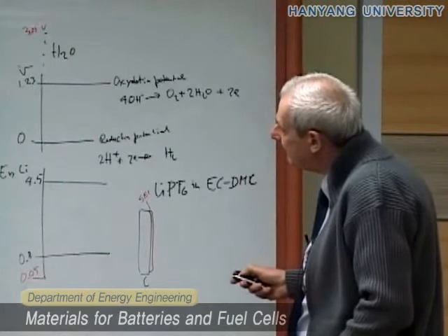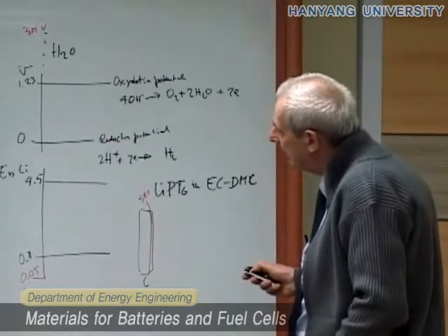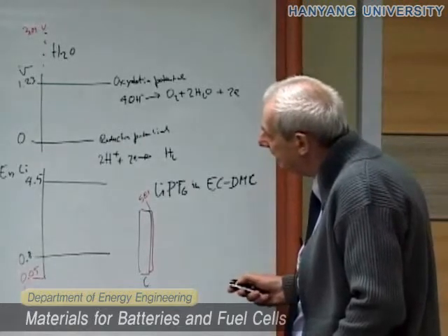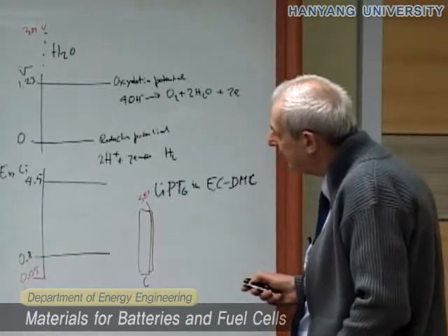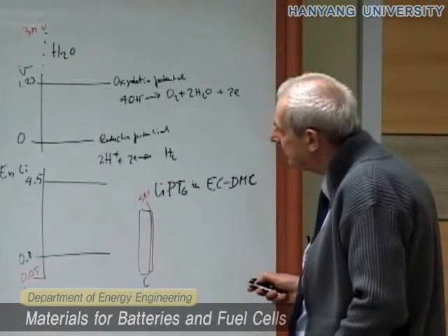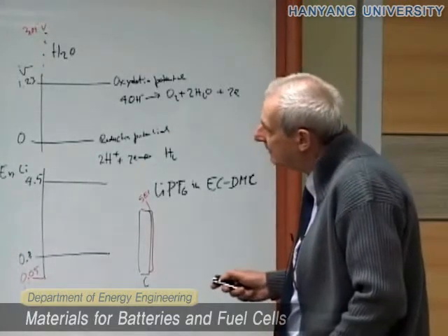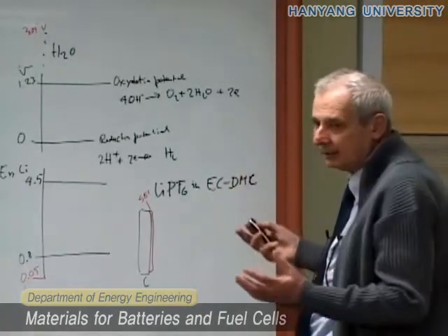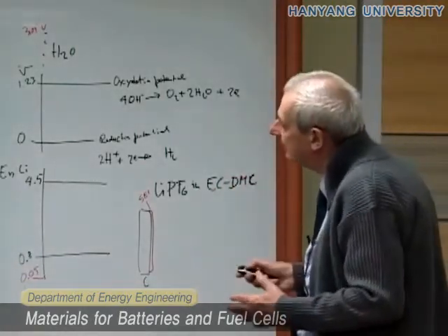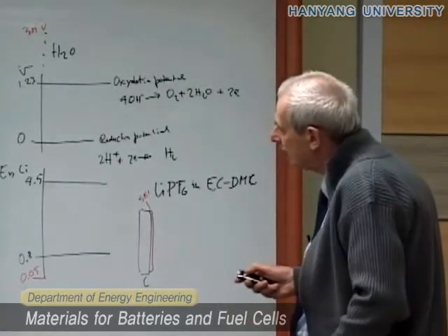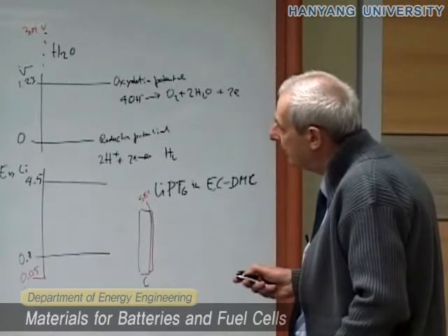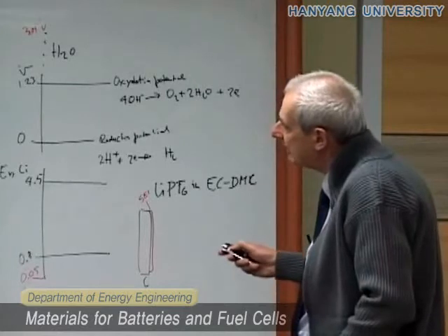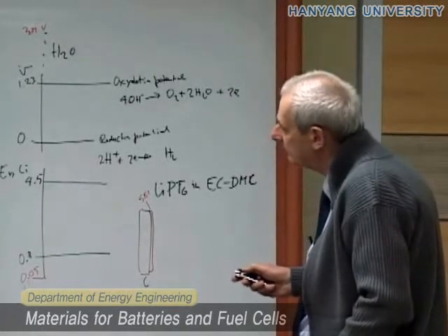These compounds react with minor impurities, for instance water, hydrofluoric acid, and with CO2 to give compounds like LiF, lithium carbonate, lithium oxide, peroxide, and lithium hydroxide. These constitute the inorganic layer here, that being porous is filled by the organic compound. So there is a connecting layer. So the lithium salt, which is present in the solution, will also be inserted here. So this gives the ionic conductivity.